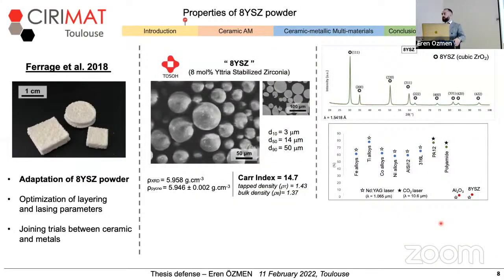8 mol percent yttria stabilized zirconia powder was used in this study. It was provided by Tosoh with an almost perfectly spherical shape and almost full density inside, with a good flowability, which is adapted for this process. And this powder was completely made of cubic phase zirconia. However, there was a limitation with this powder: its laser absorbency under the Nd:YAG wavelength.